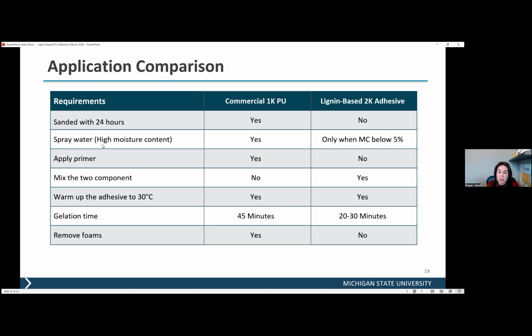Because they're moisture cure adhesives, they usually recommend that the wood should have higher moisture content. That's why they recommend spraying water before pressing the samples. What we found out is that there are adhesives, because the amount of free isocyanate is low, that are two component, mixing together. It's not as sensitive to the moisture requirements.